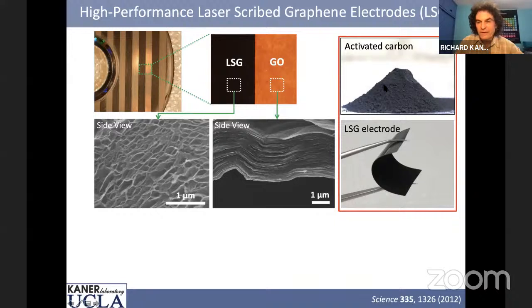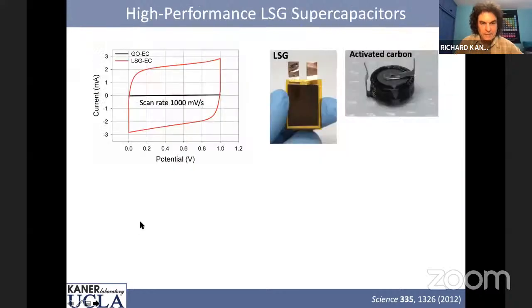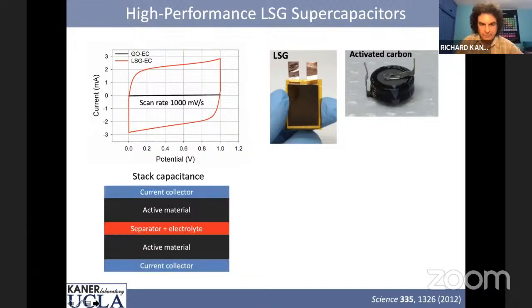So here's the activated carbon that's used in commercial supercapacitors. Here's our material on plastic that we can make little devices out of. And if we look at a cyclic voltammogram, current and potential, of course, graphite oxide doesn't store any charge, it's an insulator. But as soon as we hit it with a laser and make it conductive, you get this beautiful rectangular wave, a textbook of capacitance, and we've made a supercapacitor.